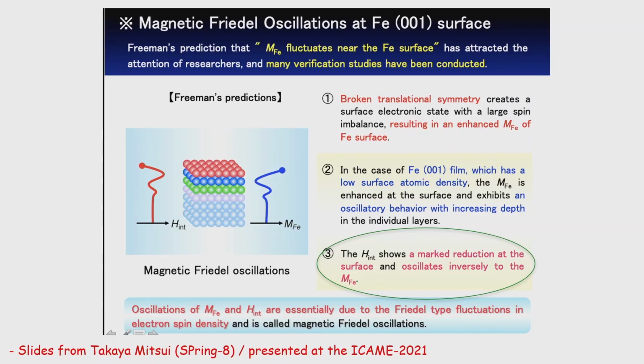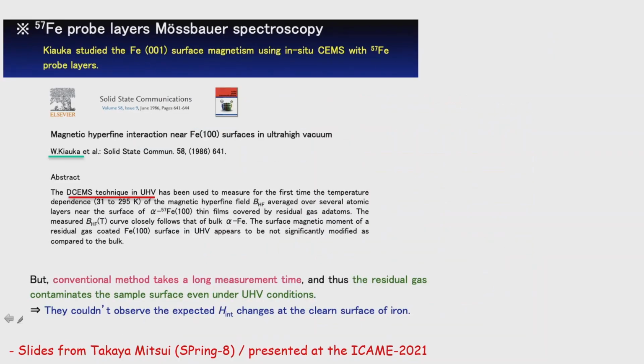It means that due to the spin density in the system, if you have a Fe layer, you should expect an increase in the magnetic moment of the iron, or a variation along the first layers, but also a decrease and oscillation of the hyperfine field in the first layers of this single crystal. These are slides from Takaya's presentation at the ICAME last year, and he sent me his presentation. He showed that there was an attempt to measure this, done by Kiauka,